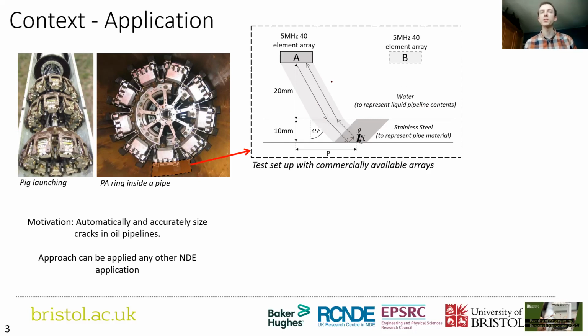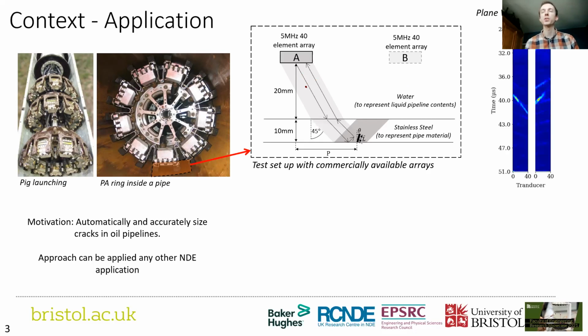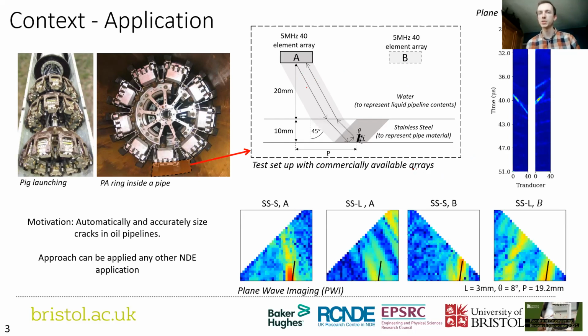We've got 2 arrays because it's normally a ring, so for each defect you can see it from an array on either side. And I transmit 1 plane wave. We'd love to be able to transmit more to get more field of view, but this thing's traveling along the pipe at roughly 3 or 4 meters per second, so you've really not got time for more than 1 firing. And then listening back on all your transducers, you've got 2 sets of plane wave capture data from any given defect. And to interpret that in a useful way, you can focus it on reception to create images.